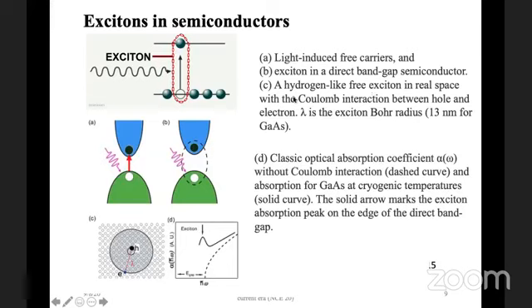Another important parameter is that this exciton, which I'm showing here, is in a direct bandgap semiconductor, and it behaves like a hydrogen-like free exciton. So we have a plus charge here, and we have an electron which moves around this hole before it recombines with it. We have a certain radius of this exciton, which we call the Bohr radius, which is around 13 nanometers for gallium arsenide. It is different for different materials because of the background dielectric constant of the material, which screens the electric field produced by these charges.